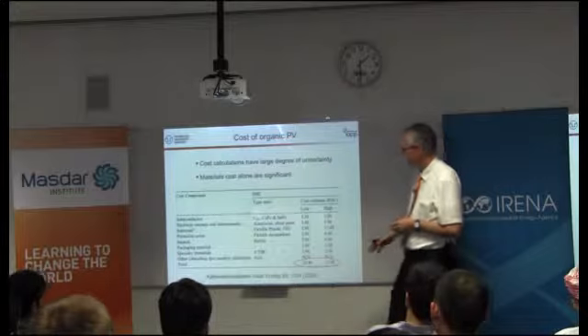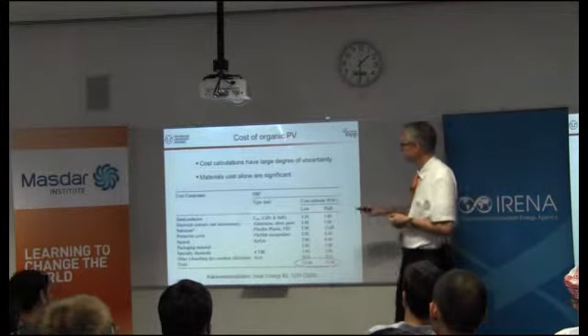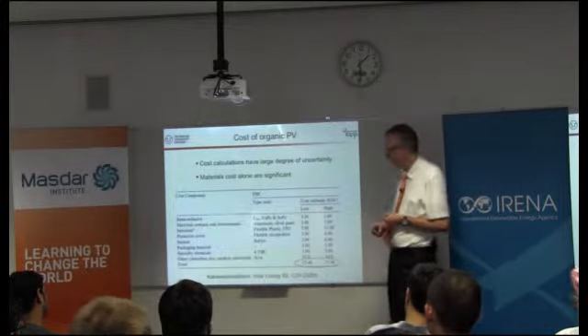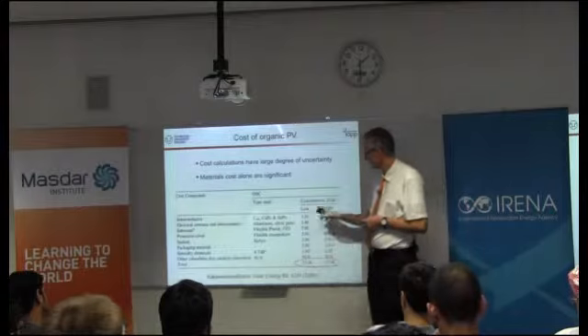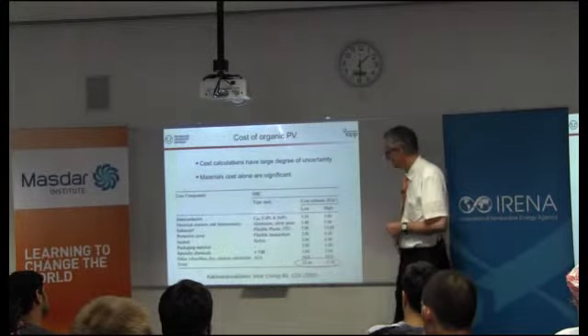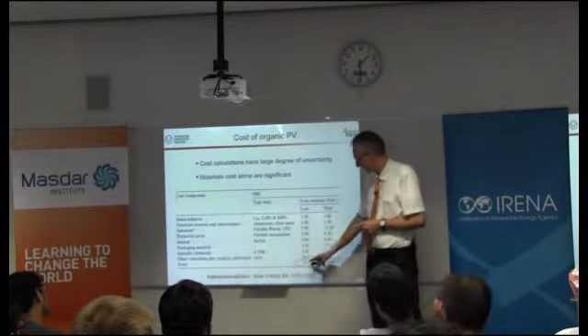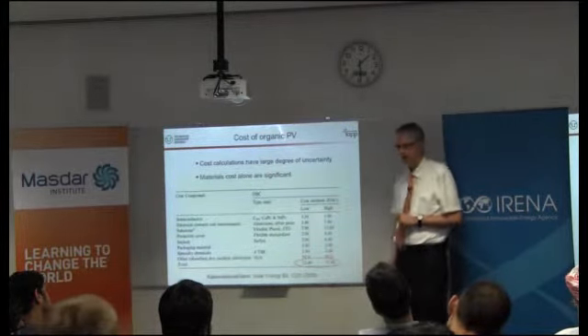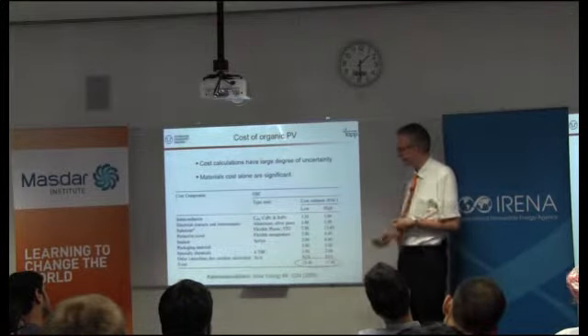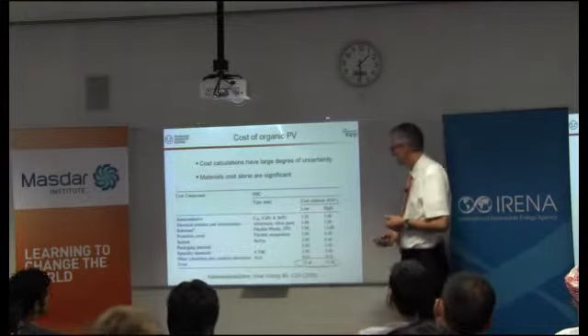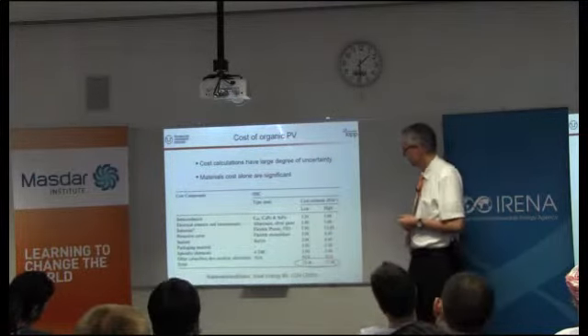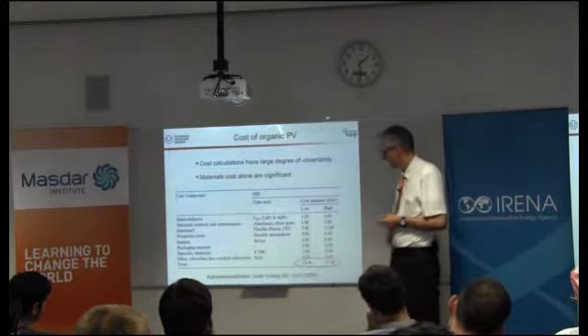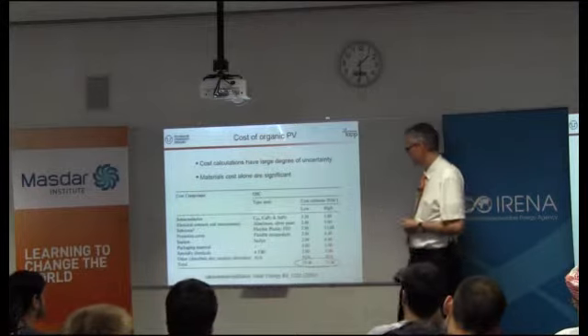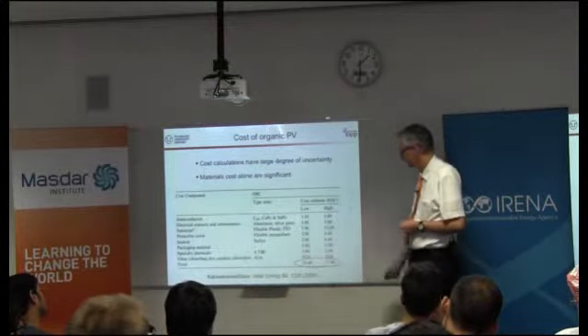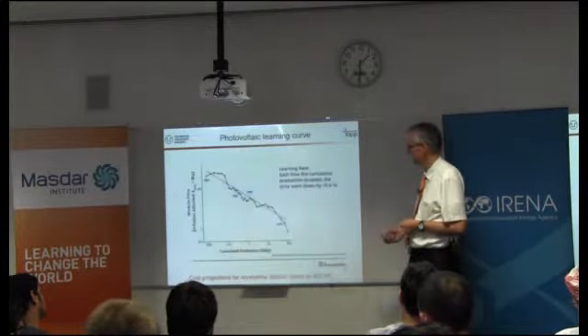For that, I show you a paper published a couple of years ago, which simply does a cost estimate of dollars per square meter for organics. And as you can see, they have a low and high cost prediction, but the basic message is somewhere between about $20 to $40 per square meter. Now, the key question is then the efficiency. If you have 10%, you get about 100 watts out of a square meter, and then you would be at 23 cents to 37 cents. If you get, say, 20%, then you would be at 11 or say 18 cents, and if I go back one slide, you would be even below the scale here.